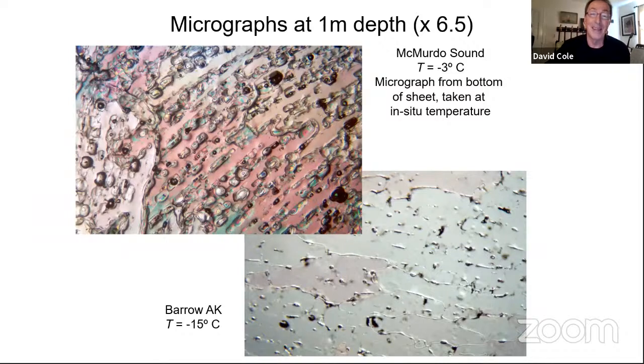If you bring a microscope along in the field, you can take micrographs such as this. This is simply to get a good picture in your mind of what happens with temperature changes in sea ice. At -3, very close to the melting point, about a meter down, which was near the bottom of this particular sheet, I was able to make a micrograph at almost exactly the in situ temperature. So this is what the brine inclusions are, all these little shapes along this sort of diagonal direction. It's drained out a bit, so you'll see little bubbles here and there, but just an incredible volume of brine at high temperatures.